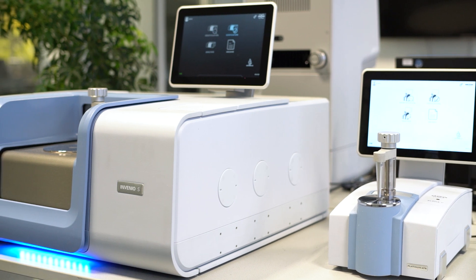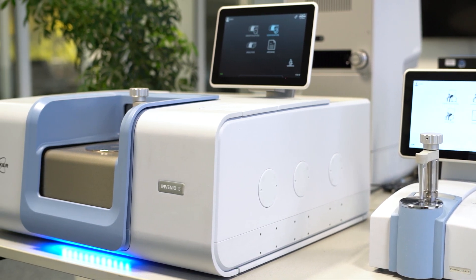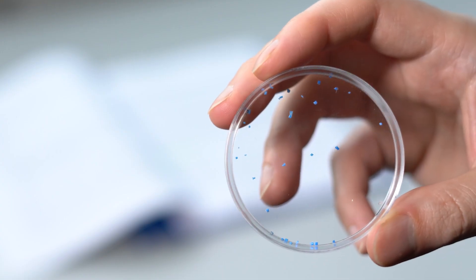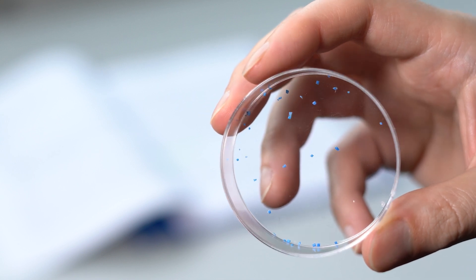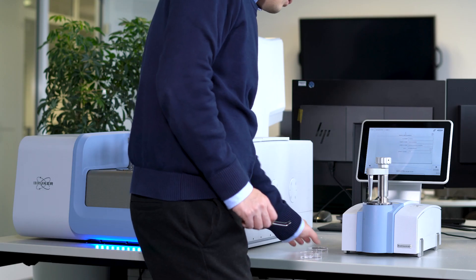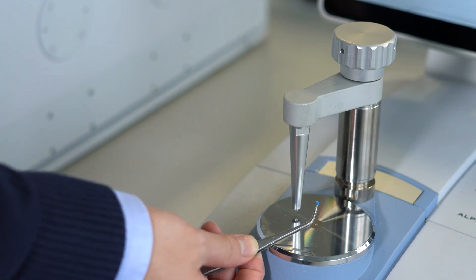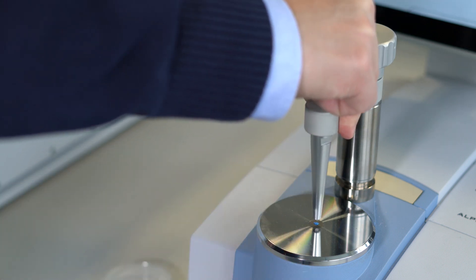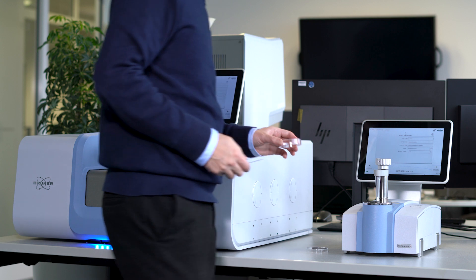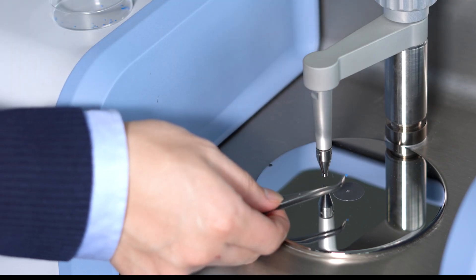For particles larger than 300 micrometers, FTIR spectrometers like the Bruker Alpha 2 or Invenio are ideal. During sample preparation, all ingredients involved in skincare were removed, leaving only these blue microbeads. These beads can now be placed on the ATR crystal using a pair of tweezers, then the sample is pressed down using the ATR clamp. For the Invenio, the process is identical and just as easy.